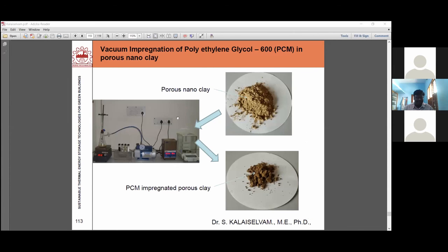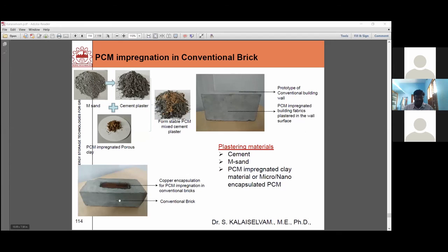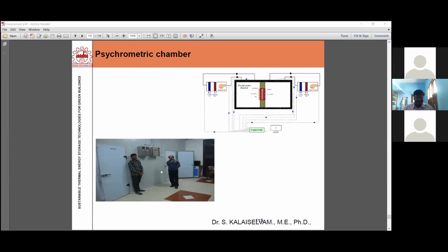So we also used the same material for building applications. This is the conventional brick material with normal PCMs. We synthesized the micro-encapsulated PCM and plastered it over the surface. We conducted a lot of studies on that. For that, we used this psychrometric chamber to study the brick material. Here, the outdoor environment can be maintained, and the indoor condition also has to be maintained. How the brick performed was studied here.